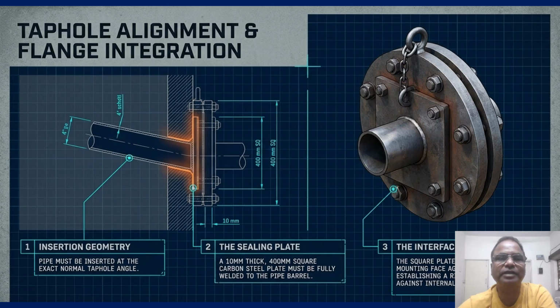The so-what factor here is safety and pressure integrity. During blowing, internal pressure fluctuates wildly. A poor seal at the taphole leads to gas leakage and potential flame cutting of the flange. We need this interface to be bomb-proof to maintain the integrity of our blast plan.